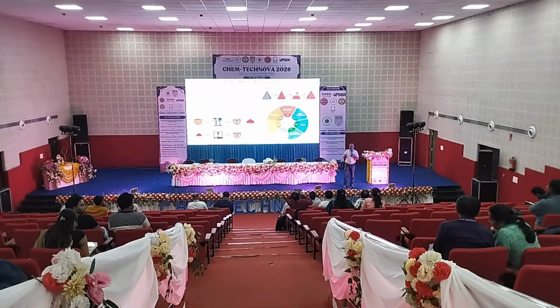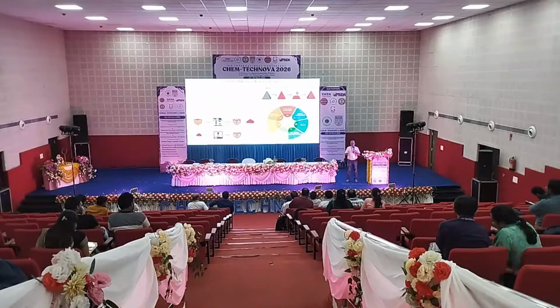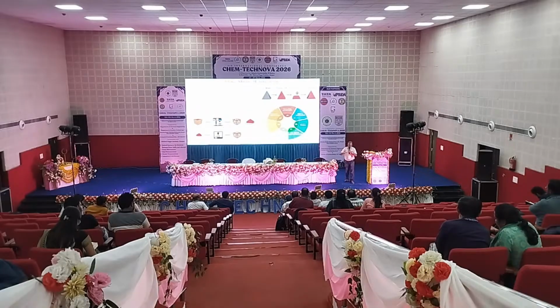Since it's a layer by layer addition in making the product, what happens? Indirectly, you are making the properties uniform through the laying direction. That is very, very important. And you have more mechanical strength between layers because it's not bulk made, whereas we are adding layer by layer. If I can make the plastics have better interfacial bonding, which means the bonding between the two layers, then it will be a superior material compared to the conventional material.